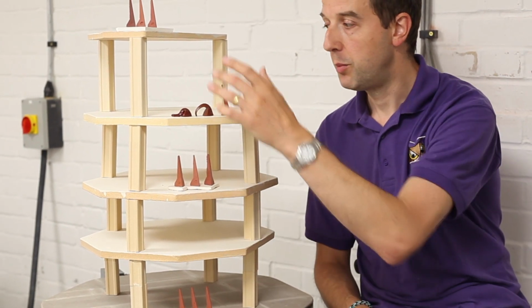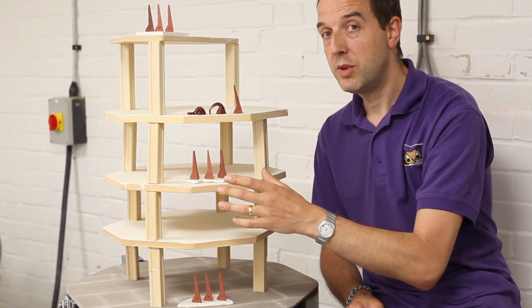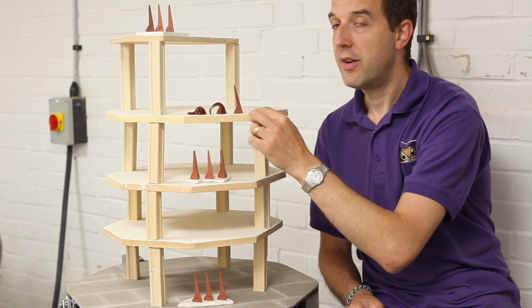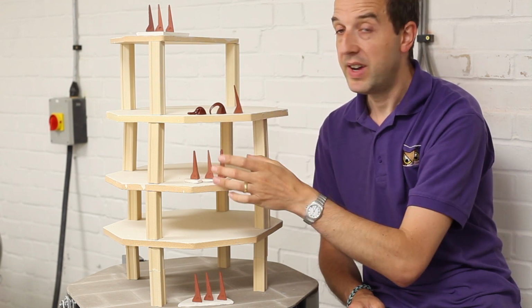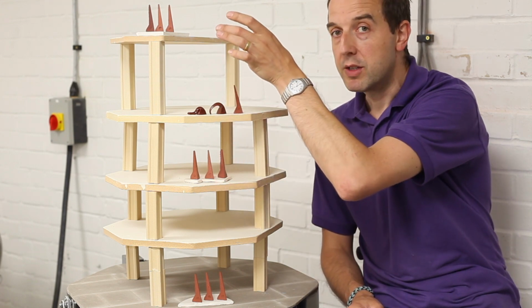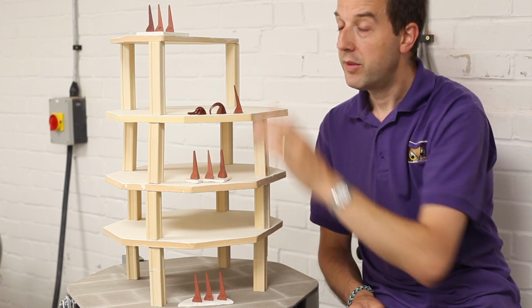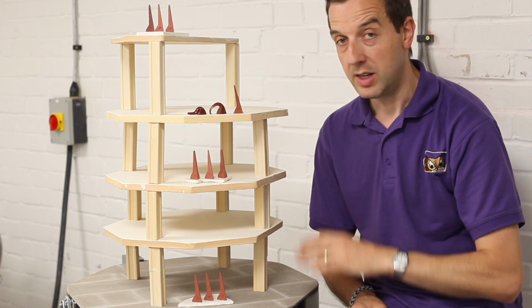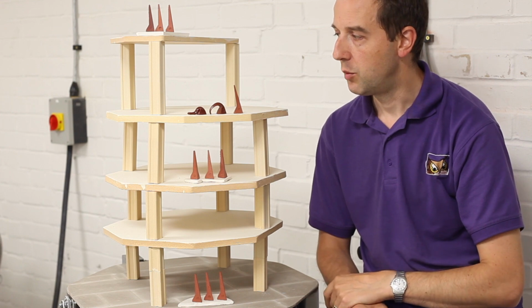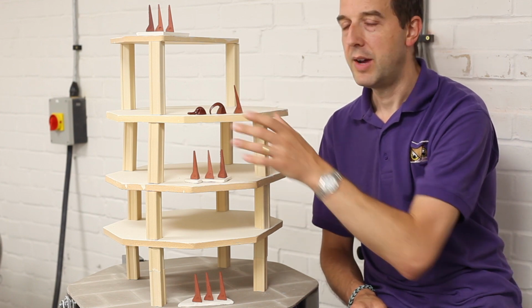What's quite interesting in a firing is to see, do you get that in all 3 parts of the kiln, at the top, middle and bottom, or do you, as you will find with many kilns, get a variation of that? Maybe you get perfection in the middle, maybe a bit hotter at the top, cooler at the bottom. Whatever it tells you is exactly what your kiln's doing, and you can do things to slightly adjust the way that you load your kiln once you have that information.